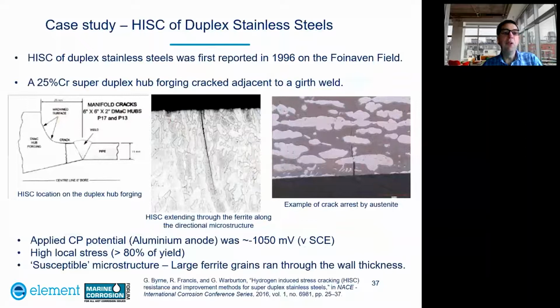The other example is HISC of duplex stainless steels. So HISC of duplex stainless steels was first reported in 1996 on the Foinaven Field. So on this example, a 25 chrome super duplex stainless steel hub forging cracked adjacent to a girth weld, as shown on this sketch here.